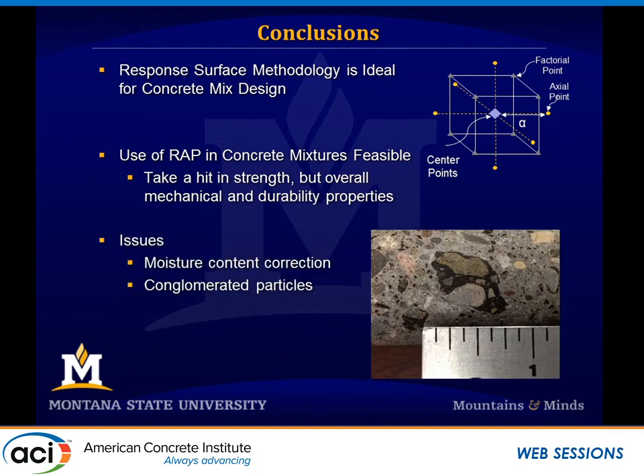Use of RAP in concrete mixtures is feasible. You take a hit on strength, but overall the mechanical and durability properties show that it meets the minimum specifications. It should work well as a concrete pavement. And then the issues we had: primarily, one of our conclusions is why we think our concrete in particular was taking hits on strength, and this is also consistent with what Illinois found. They had some big conglomerations of asphalt and fine aggregates that were counting as coarse aggregates.